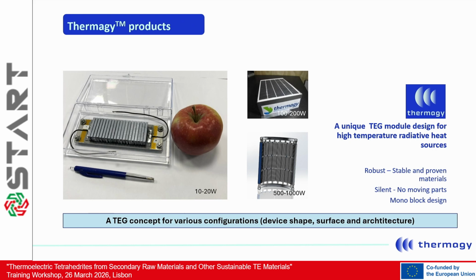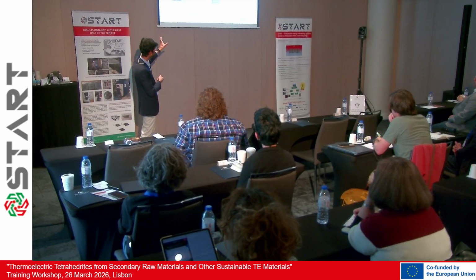We're able to string multiple of these modules together. So here you can see 15 to 20 modules to get up to 100 to 200 watts of electric. We also can do up to 1 kilowatt systems in cylindrical fashions. Our main value proposition is that it's a unique TEG module design for radiative heat sources with the silicon germanium material. It is a solid state conversion technology, so that's one of the main advantages of thermoelectric generators. And this can also be tailor fit, so device shape as well as the surface, for various incoming heat flux densities.